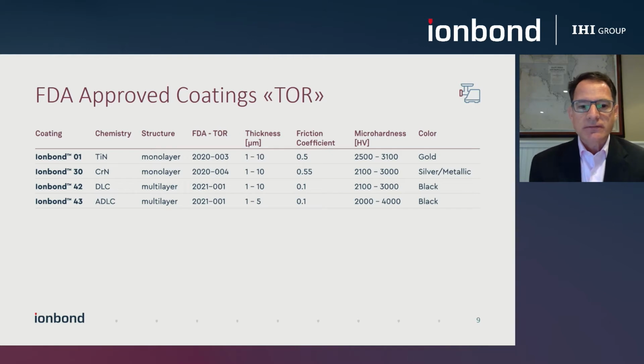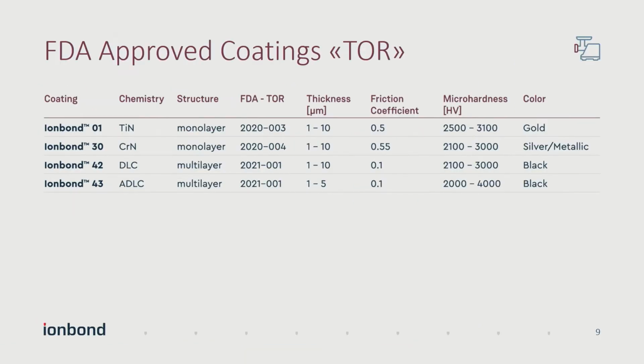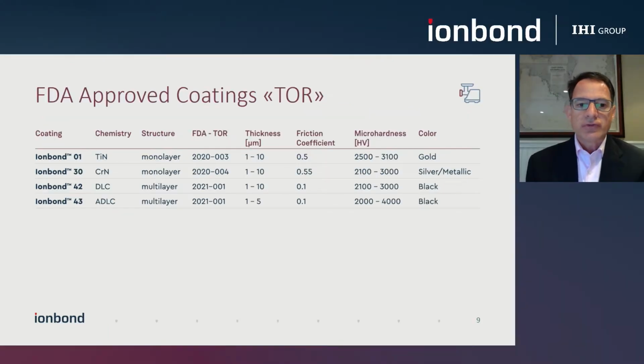If you're not familiar with these types of coatings, these are normally thin film coatings, as we would call them. They can be anywhere from a thickness range between 1 to 10 microns. As a result, these coatings have unique functional properties associated with them. As you can see here, the friction coefficient of titanium nitride is around 0.5. And we measure microhardness in all of our coatings in Vickers. Depending on the structure of the coating, we could typically be in a range of around 2,500 to 3,100 Vickers. Another attribute associated with each of these coatings, by combining the different elements, which we'll go into in more detail in the follow-on materials, is a color. The color would be gold in this case.